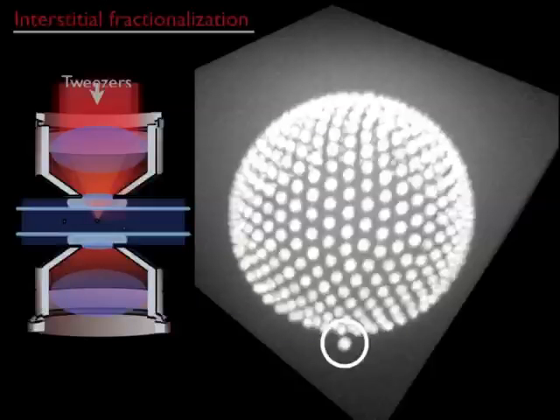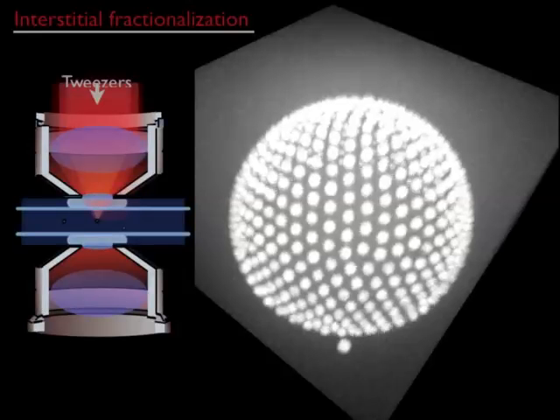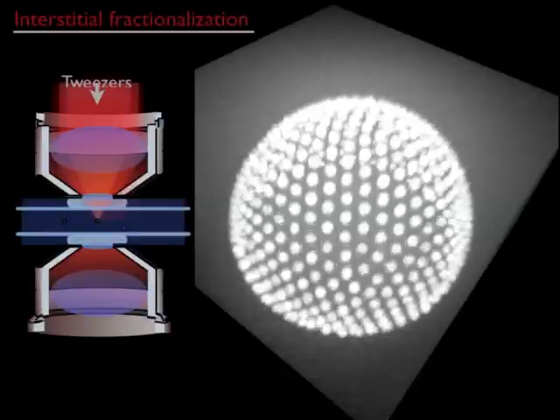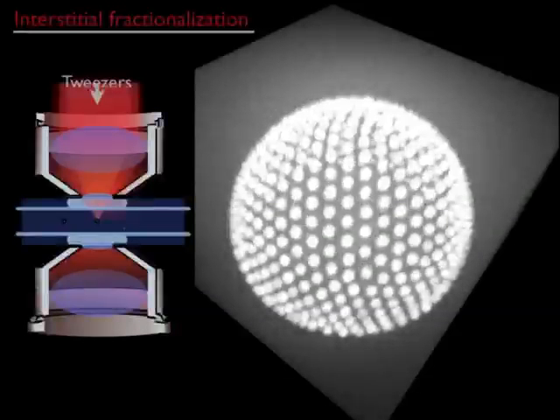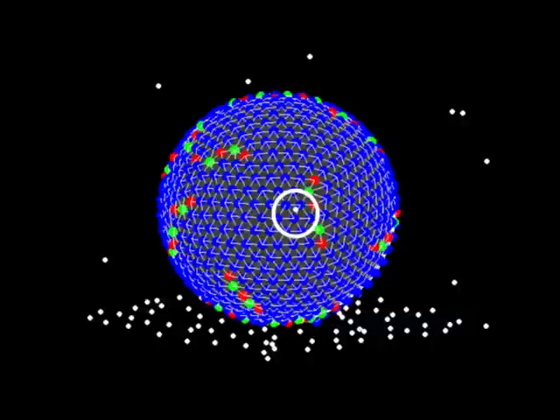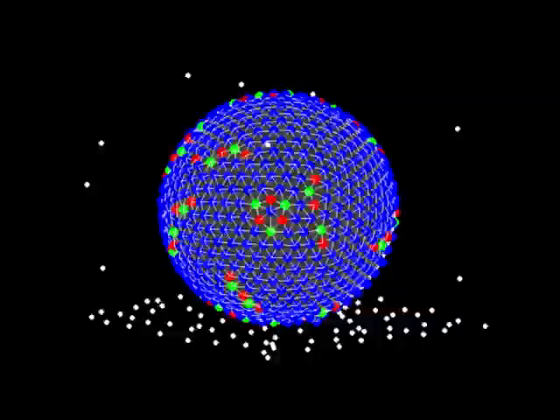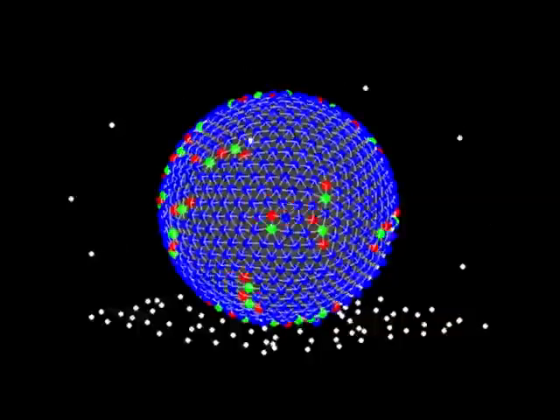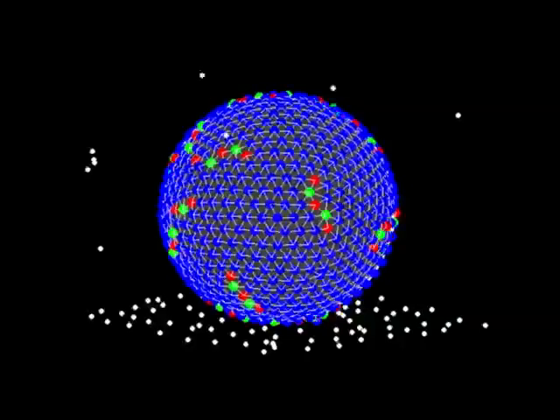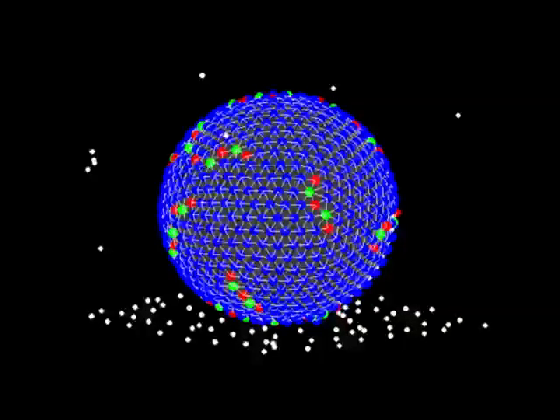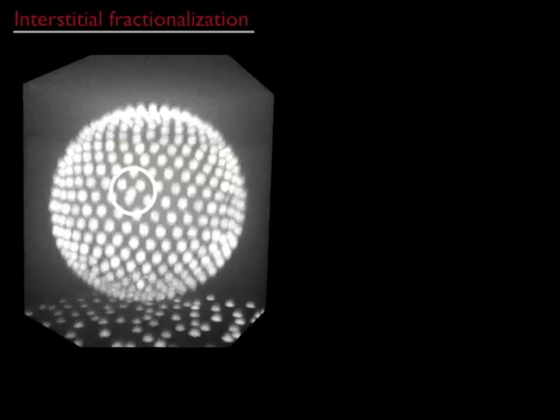Now the question is, what happens if you do it on a curved surface? Here you go. A laser tweezer holds this here, and you approach the surface, and you see it goes in, and everything changes around. It's not clear where it is. Again, it's a problem of looking to see what happens by triangulating. What happens is it goes in, creates 3 dislocations, and there's a scar over here, and it just gets absorbed in the scar. That's not so unusual. It only happens on the curved surface, because you have to have the disclinations there, and that means you have some strain field, and the strain field acts on these to move them, to essentially absorb them. On a flat surface, you don't have that. So that's one thing that happens, and it happens most of the time.